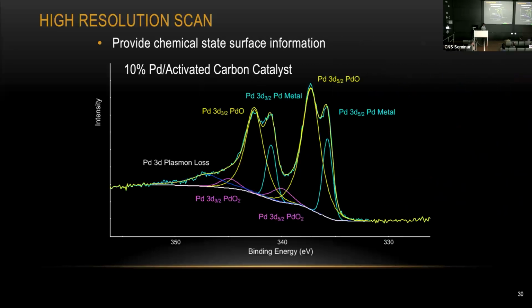So that's our second data type. When you do XPS measurement, that's the so-called high resolution scanning. People also call it narrow scanning because you are only focused on a very small range. This data is taken from the same sample, 10% palladium in carbon catalyst. By doing the high resolution scanning, the whole idea is you can do some peak fitting, some deconvolution, and you can try to determine some chemical molecular information.